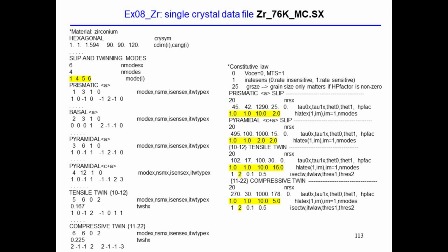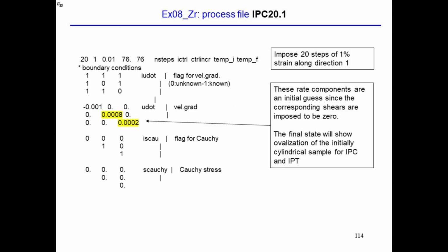law. And these 2 numbers really are 2 thresholds. We don't allow for twinning until 10% of the volume of the grain has been compromised. We don't activate the twin right away, except for the volume fraction transfer scheme. We start early. So this is the in-plane compression, 20% in the direction 1. There's nothing strange here except that now we are putting a strain rate epsilon dot 11, which is 10 to the minus 3.